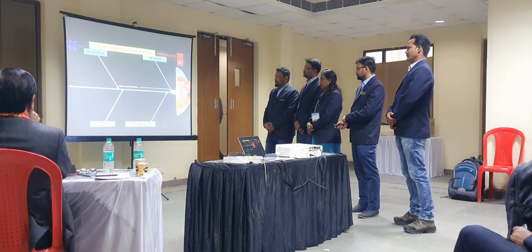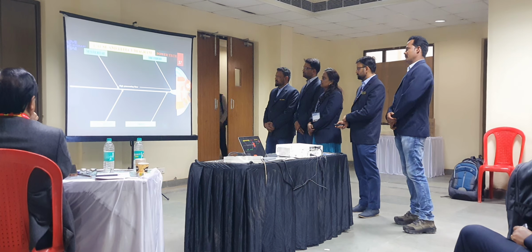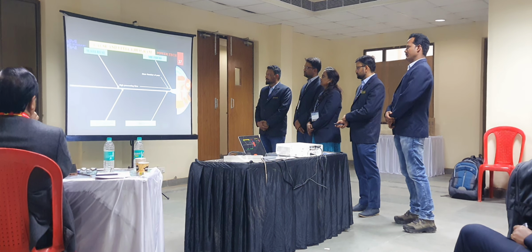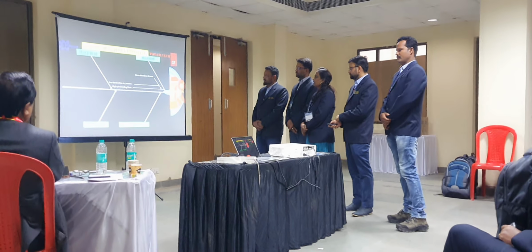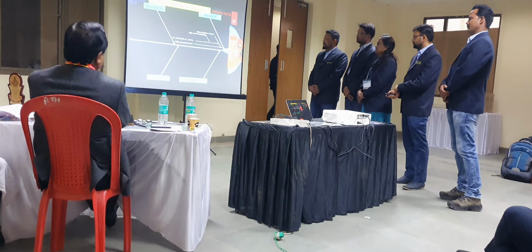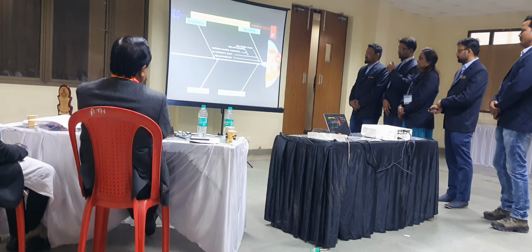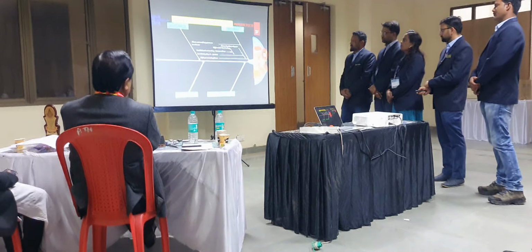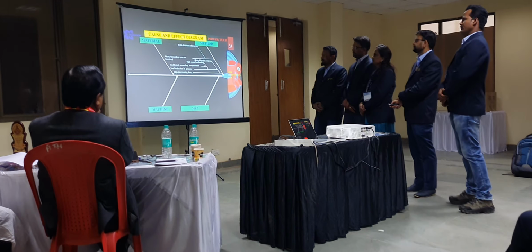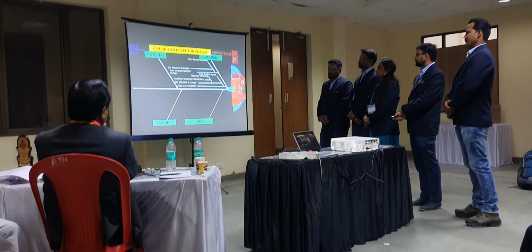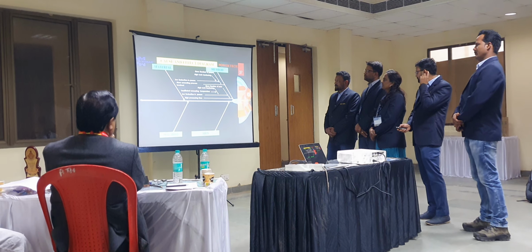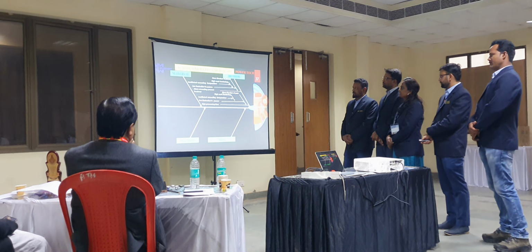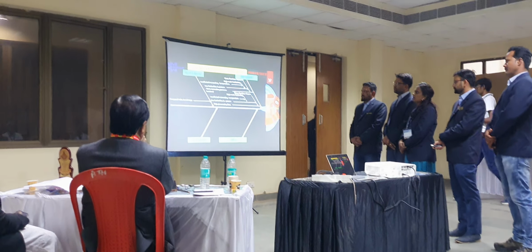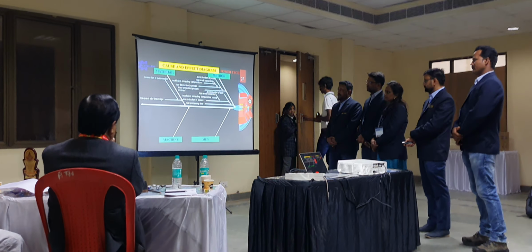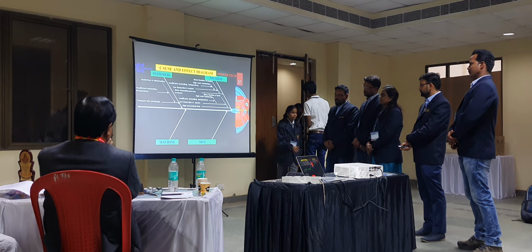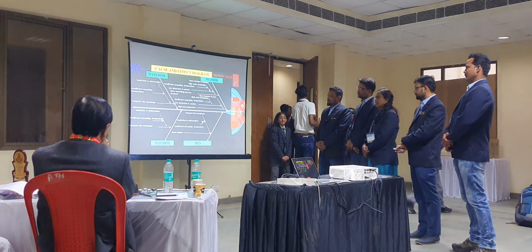For less productivity rate, in case of method, one of the possible causes is high processing time. Why? More number of passes. Why? Low reduction in passes. Why? High work hardening. Why? Insufficient annealing temperature. Another possible cause is more annealing process involved. Why? More number of passes. Why? Low reduction in passes. Why? High work hardening. Why? Insufficient annealing temperature. In case of material, a possible cause is frequent wire breakage. Why? Restriction in deformation. Why? Insufficient annealing temperature. Similarly, in machine and measurement.